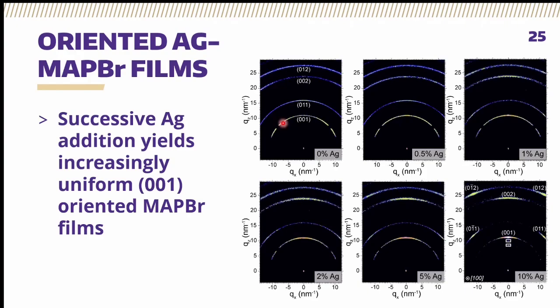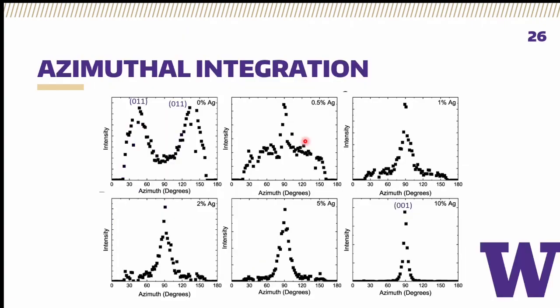If there's a spot, there's oriented texture in a specific direction. And with this color map, with any color map truly, the eyes deceive. So what I really wanted to do is we took a certain range of 2 theta or Q, between this Q here, I think it's maybe 11 or 12, doesn't exactly matter, and the Q ring here. And we integrated X-ray counts as a function of the azimuth angle, basically the angle from, so this would be an azimuth of 0, this would be an azimuth of 90, this would be 180. Okay. And doing that, we could more easily see the orientations of our thin films.